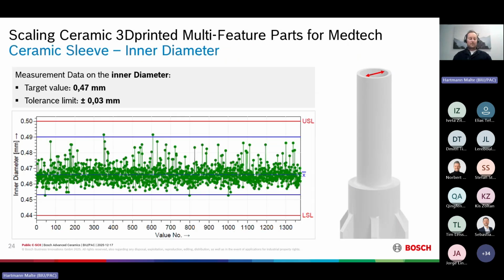And this is the data that was the result of this evaluation. The target value here was 0.47 millimeters, and the tolerance requirement on that inner diameter, which we can see on the right, was then 30 micrometers. So yeah, we can see all parts of this print job are within specifications because of the tolerance limits indicated in red. The variation is within the tolerance limit, and we see only very low variation around the mean value of just a few microns.